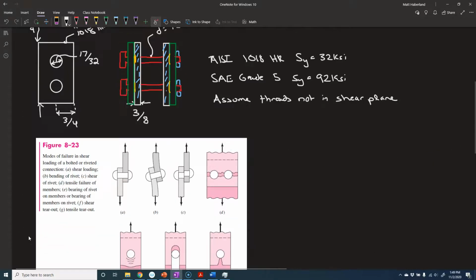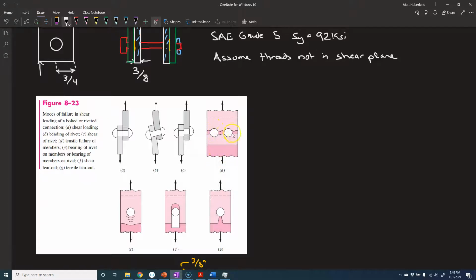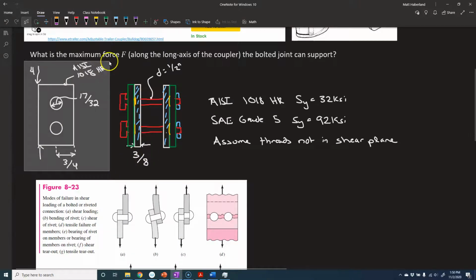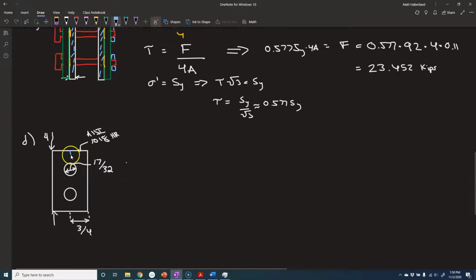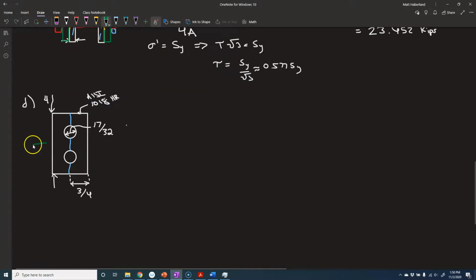Okay, next case. The next case is that the material surrounding the bolts fails. And this looks like a tensile sort of failure, right? Because we're going to be analyzing an area here, which we take to be the minimum area that we can find, such that the two parts are going to separate in tension. And the surface normal of those is in the same direction as the applied force. So we're going to have a normal stress here. The relevant diagram for us is this one. We're talking about a failure here on this plane. And the force is being applied in this direction on the coupler. And so the surface normal is aligned with the force. We've got a normal stress in this area.